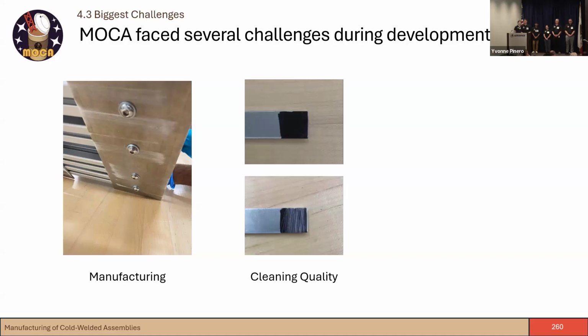We also needed to come up with a way to determine how well our cleaning mechanism worked. There's not really much data on how well one pass through the cleaning mechanism works, or how many passes of a brush it takes to remove an oxide layer. So to solve this, we decided to mark our members using Sharpie or Dykem, and then pass it through the cleaning mechanism and see how much of that layer is removed and how many times we would want to pass it through in order to completely clear out that area. Next, please.